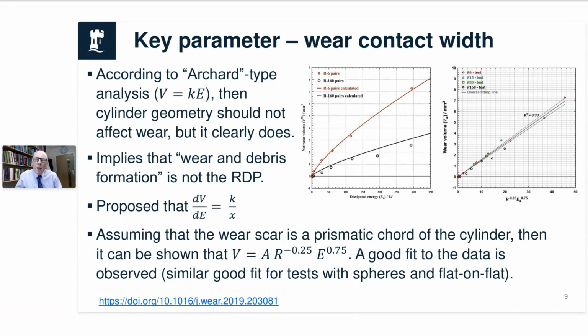We proposed then a relationship based on that, and there aren't fitting constants. That relationship that I've got there on the slide says V is equal to A R to the minus 0.25 E to the 0.75. That isn't fitting data. That's simply a geometrical expression, and you can go to the paper to see how we pulled those sorts of things out.